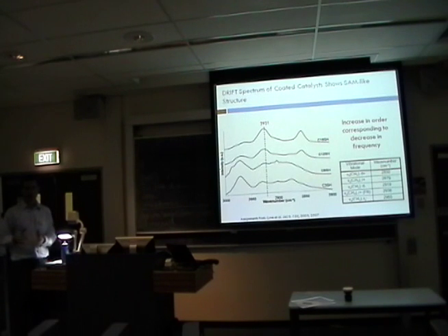And so what we think is actually happening here, although this is pretty recent work, is that as we form these ordered arrays of bound organic molecules, we're forming well-organized channels that allow the molecule to move in between chains and do the reaction. Whereas when things are more disorganized, we don't have those nice uniform channels that allow access of the molecule to the surface, where we have a highly selective reaction because of the interactions with the self-assembled monolayer.